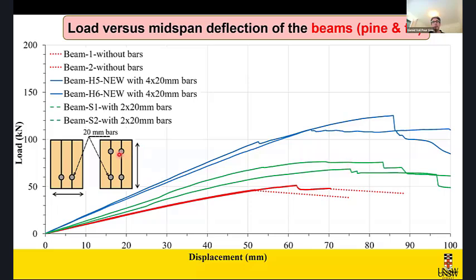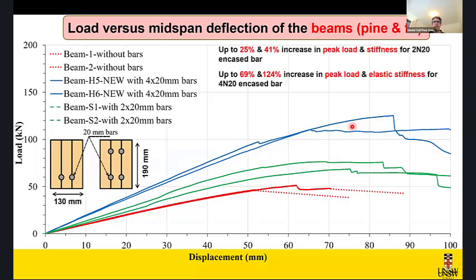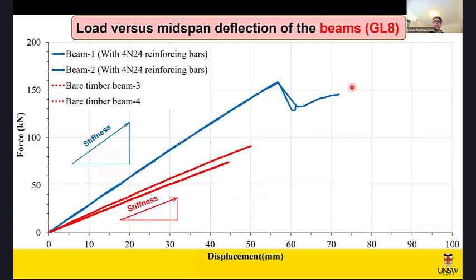And then when we have reinforcing bars in both compressive and tensile zone, the alternative on the right, which is a 190 millimeter deep beam, the peak load goes close to 115 kilonewton, which is a substantial improvement in strength. Now, if you want to see what the percentage of improvement in peak load and stiffness, we saw 25% and 41% in peak load and stiffness in the case of singly reinforced, you see on the left, and in the case of doubly reinforced, 69% and 124% improvement in peak load and stiffness.